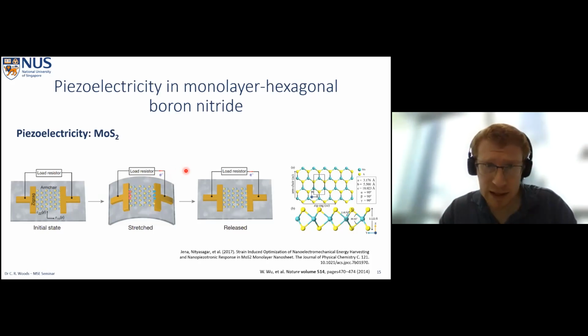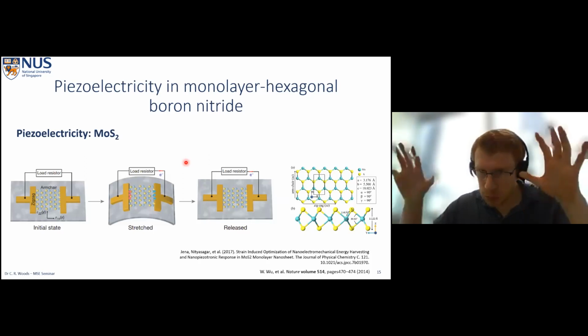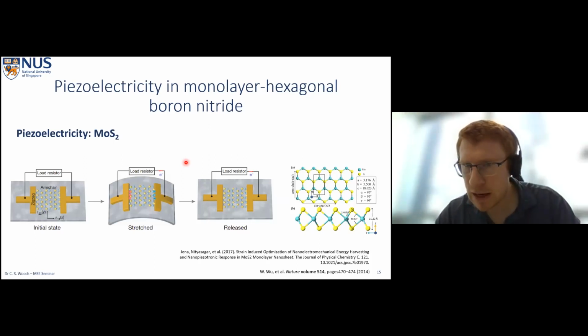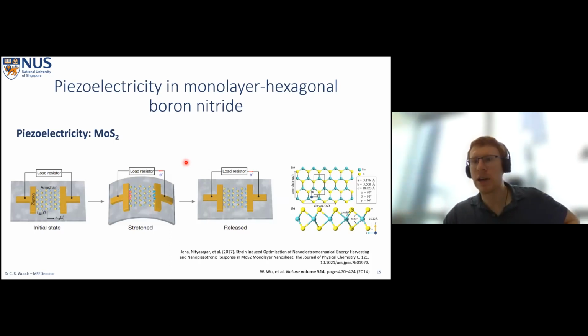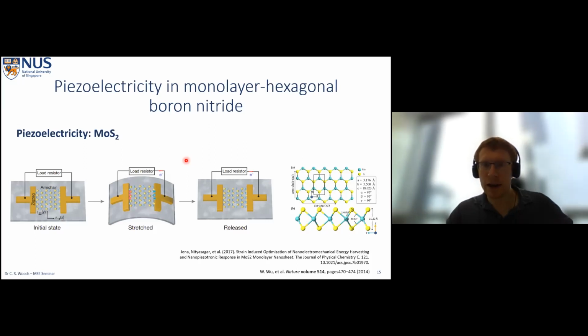I've spoken about a few things, like we use just the bubbles, which are kind of an incidental part of our samples, but people can use polymers and stretch the substrate, like in MoS2. People also fabricate nanostructures and then place their 2D material on top of the nanostructures. And this creates large strains when the crystal is required to conform to a non-flat substrate. But to be honest, the answer to the question about creating inhomogeneous strain is a really big one. It's a really good question, and it would take quite a while to give a comprehensive answer, but there are lots of different ways to do so.